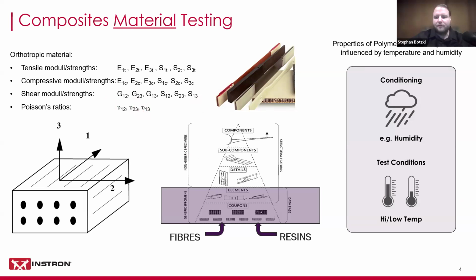And then on a micro level, we're interested in things like the fracture toughness of the laminate, as well as the compression after impact strength for aerospace applications, for example, and then also filled hole, open hole tests, depending on how the material is going to be used in the end application. We also need to simulate a lot of times different temperatures and humidity levels because they also affect the properties.